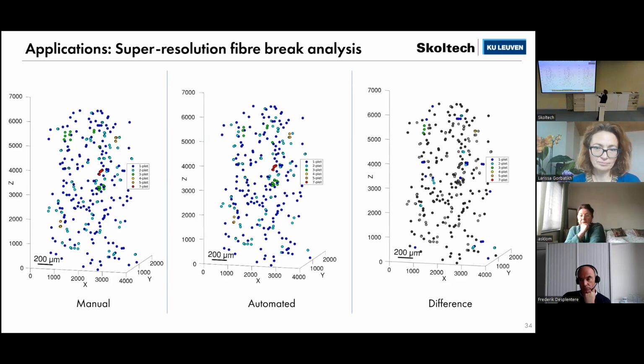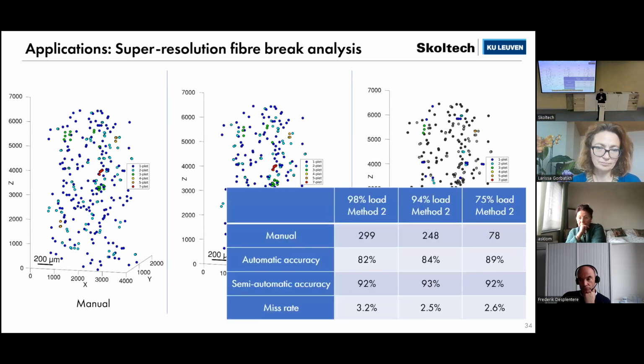dots. And if we compare it using metrics, using the fully automated algorithm, we have 82% of accuracy. But when we treat large objects manually, the automatic algorithm takes less than a minute, semi-automatic takes approximately 1-2 hours, not weeks, as for fully manual, and we have in the end less than about 3% of missing rate.